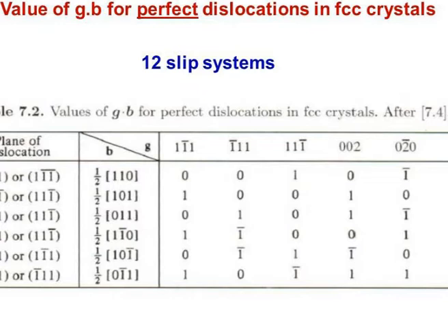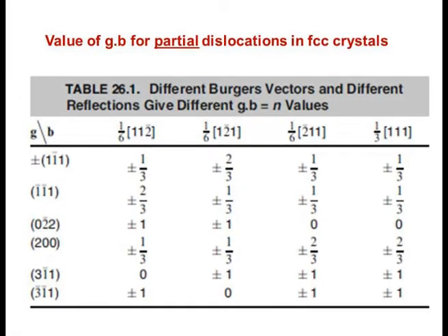So when we have taken pictures like this systematically, we can compare with this table, and on this basis identify what that exact G vector is, from which we can also find out the Burgers vector of the dislocation. The same sort of calculation can be done for partial dislocations also. We can find out the conditions, G vectors and Burgers vector.